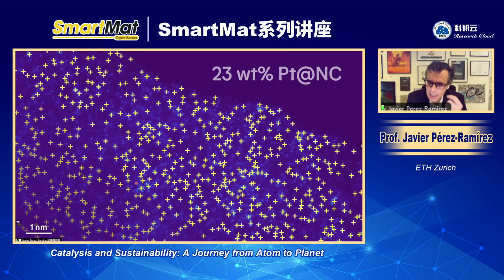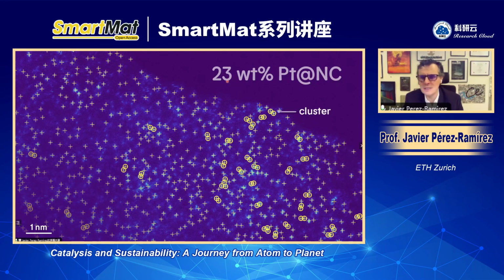Now, the issue is that if you analyze a little bit more carefully, you will like to know, do I have any clusters in this sample? It's actually quite fair to say that perhaps there are some clusters because, you know, there is a huge metal content, right? Now, our algorithm is able to detect clusters. And let me show you how we do this. The crosses that you see now with circles are actually clusters in the material. The rest are single atoms. So about 10% of this sample is clustered, 90% single atoms.